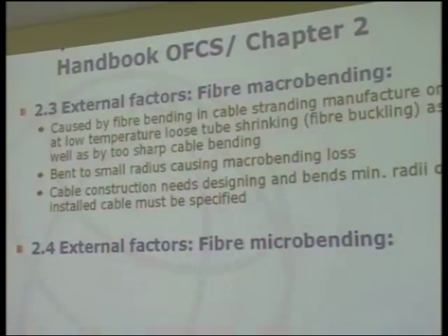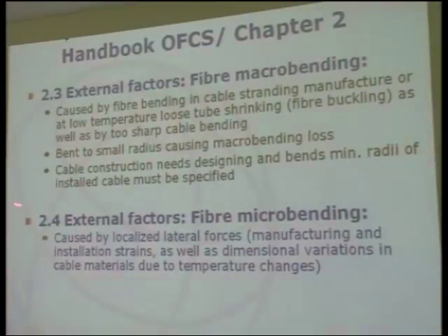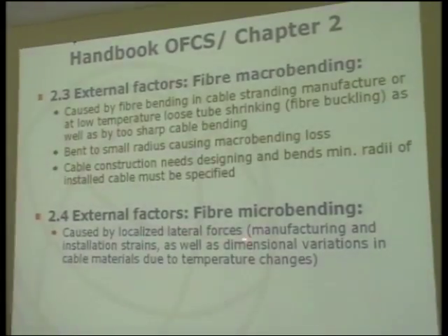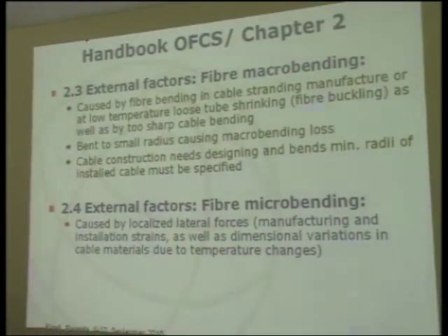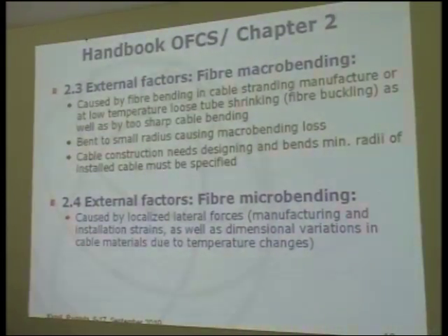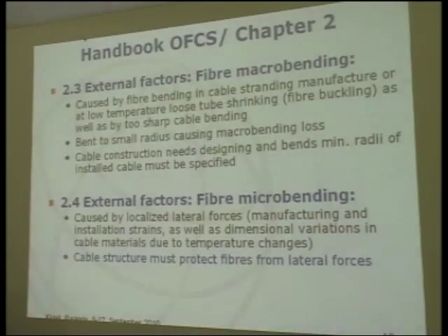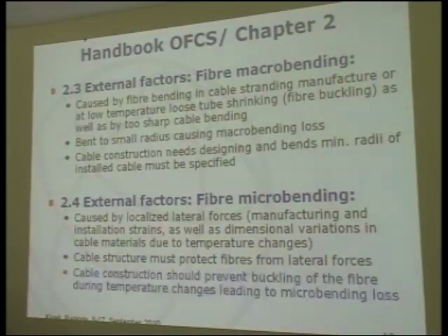We can also have some attenuation increase caused by micro bending, and that is caused by localized lateral forces, manufacturing and installation strains, as well as dimensional variations in the cable materials due to temperature changes. A cable structure must protect the fiber from lateral forces, and the cable construction should prevent buckling of the fiber during the temperature changes leading to microbending. Because if you have, for instance, a low temperature effect, not only can the fiber buckle and create a macrobending issue, because it's pushed then to the inside wall of the loose tube, you will also have a kind of microbending effect, because you have stresses working on the fiber.